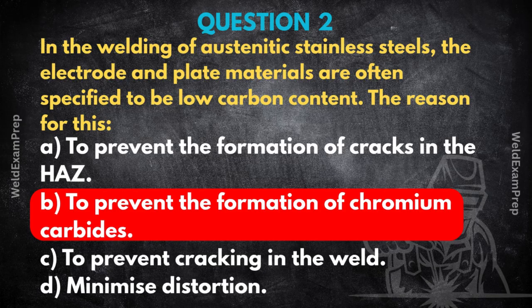And chromium is the key element for corrosion resistance. Precisely. It forms a protective passive oxide layer. Yeah. If you pull chromium out of those areas at the grain boundaries, they become vulnerable, like little highways for corrosion. This makes the steel highly susceptible to intergranular corrosion in aggressive environments. Wow. So using low-carbon materials, the L grades like 304L or 316L, drastically reduces the amount of carbon available to form those carbides. It preserves the chromium where it needs to be, maintaining the corrosion resistance. Okay, let's unpack this a bit.